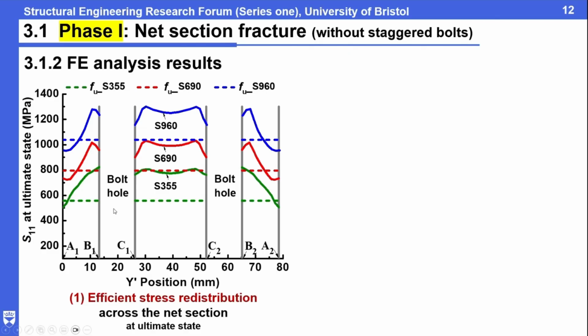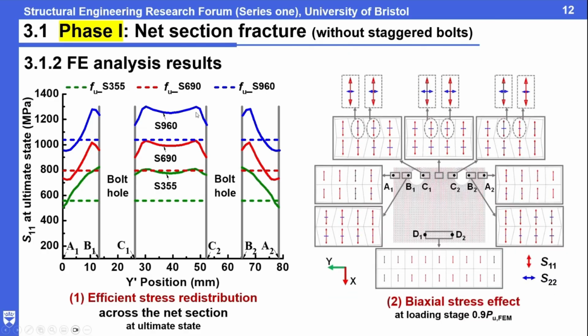And another effect is about why they can develop so much higher. When we look further at the stress distribution across the critical net section in detail, we find that at the stage of the nearly ultimate state, under tension, the critical section's stress distribution is not pure tensile stress. It's biaxial stress, with a little bit of tension in the other direction too. This is because the hole is here.